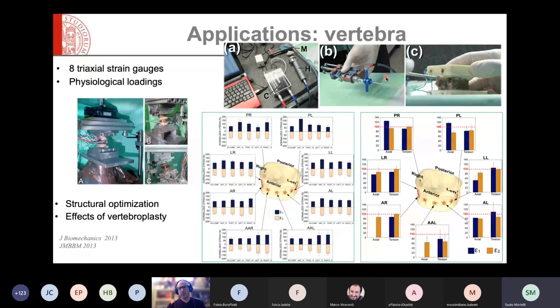We applied this method also to investigate the effect of cement augmentation. This is a project we did together with the group of Stephen Ferguson in Zurich. This is a system for delivering a controlled amount of cement in the vertebra, and these are the strains modified in the vertebra from the natural condition to the augmented condition. And essentially, we found that if augmentation is not properly performed, you have a worsening rather than an improvement of the loading condition inside the bone. Again, this was part of also a validation study, so also here we had an intensive interaction with the FE modeling.